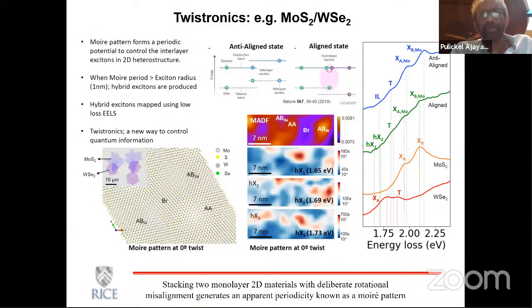And finally, very recently, people have been trying to think about this idea of twistronics. So if you take two layers and then start to twist, or start to rotationally disorder, then you start getting these moiré patterns, and they apparently have a very strong effect, creating some very fascinating properties. Maybe one could think about interlayer excitons when you are twisting them. There are some correlated systems which even show some superconductivity in bilayer twisted graphene.